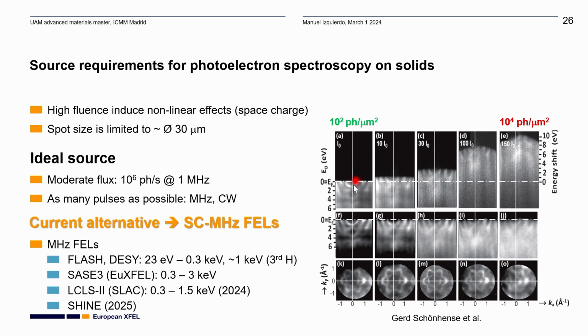If you take a given sample and you excite it with something like 10 to the 2 photons per square micron, then you are going to measure your valence band with high fidelity, and you can also measure your Fermi surface. If, on the other hand, you start increasing the intensity, you multiply by 10, you see that some electrons go above the Fermi level, which is not good. As you increase further, you end up in this situation where the valence band and the Fermi surface are very much distorted, because you produce so many electrons and there are so many electrostatic interactions between the slow and fast electrons that in the end your image is blurred. If you know your system like this one, you can apply some corrections and do the measurements also with high flux. If your system is new, then you are lost and you will never be able to trust it.